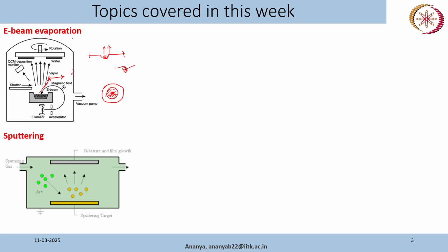So for the first few depositions, you can measure the thickness experimentally, and then you can compare with the thickness shown by the crystal monitor, and then you can find the factor. Okay, say if the crystal monitor shows 100 nanometer, we are actually getting a thickness of 110 nanometer. So you know the factor, and then you can use that factor to stop your deposition, you can use the shutter, so that you get the desired thickness from the next time onwards. Okay, so this is about the different components in a thermal evaporator system.